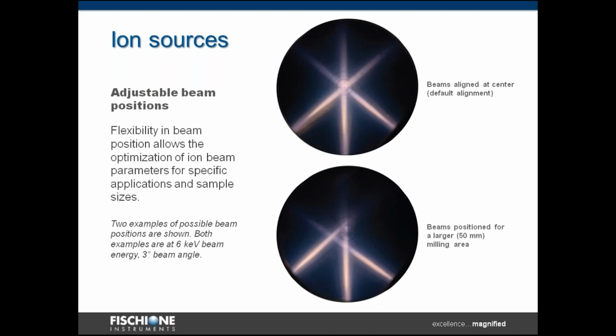This slide shows the relative position of the ion sources and ion beams. And this essentially is the secret sauce of the instrument. If you look at the beams in the upper position, you can see them aligned so that they cross at the center point, which is the axis of rotation. In the lower image, the beams are configured sort of in a bird foot type of configuration, and that allows the ions to project all the way out to the periphery of the sample. That's what produces the large milling area, and that's something that Pavel will be talking on in a little bit.